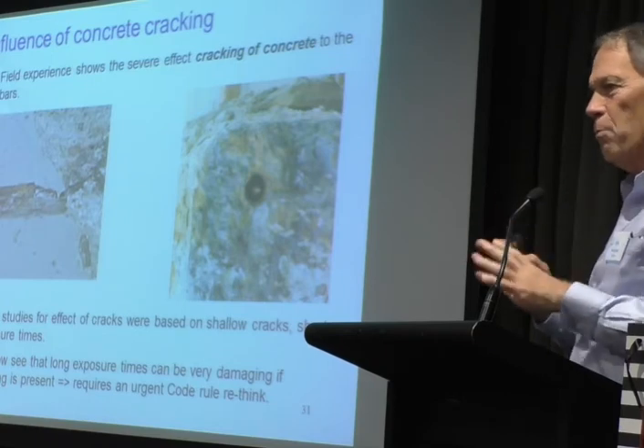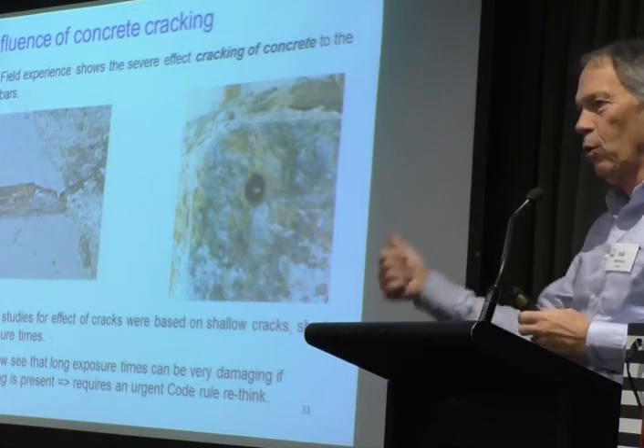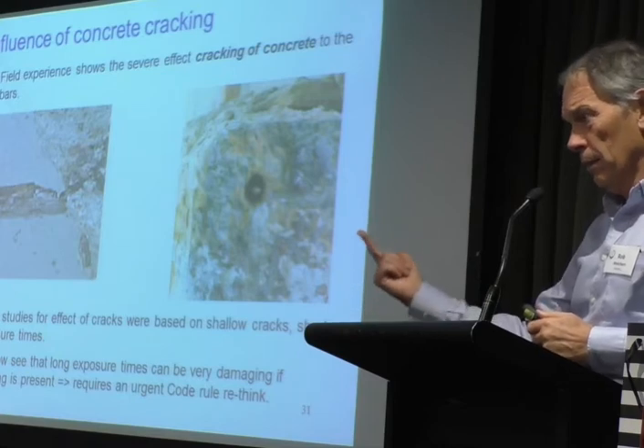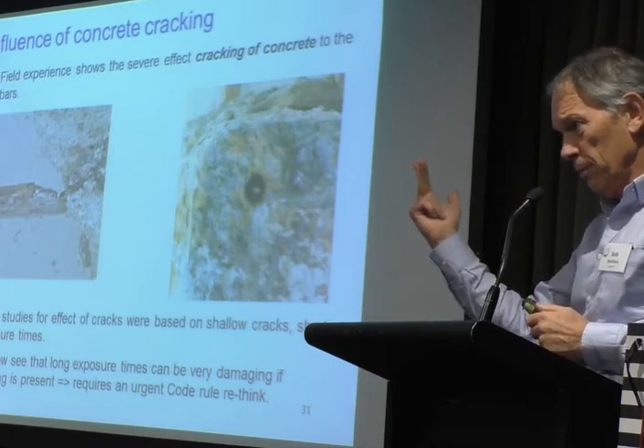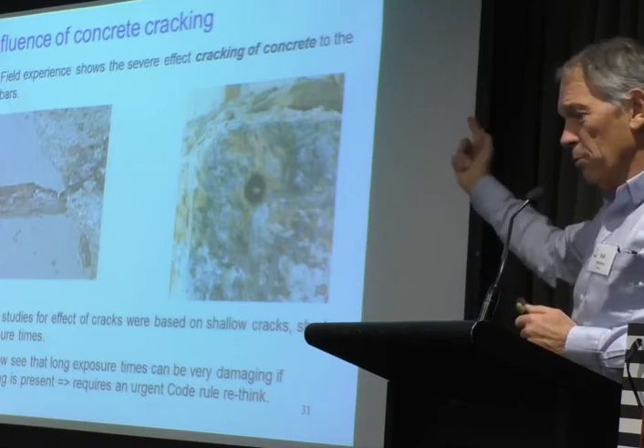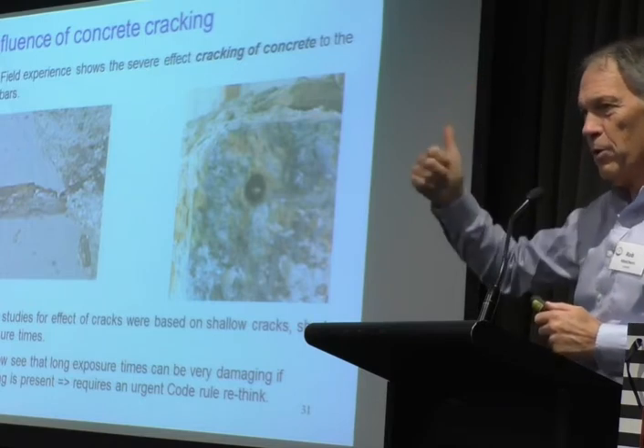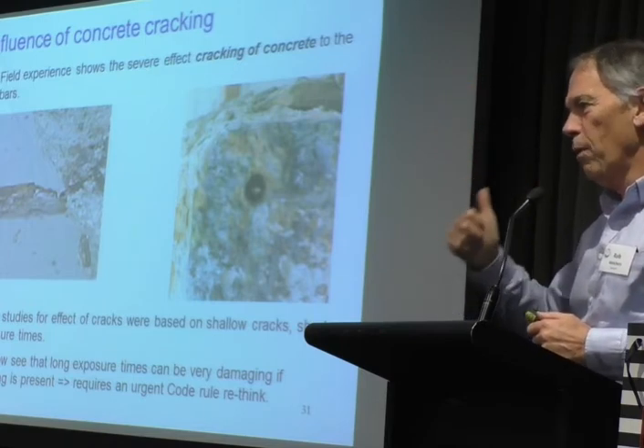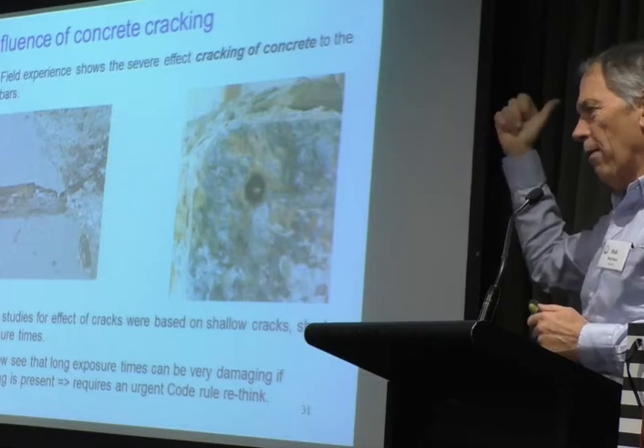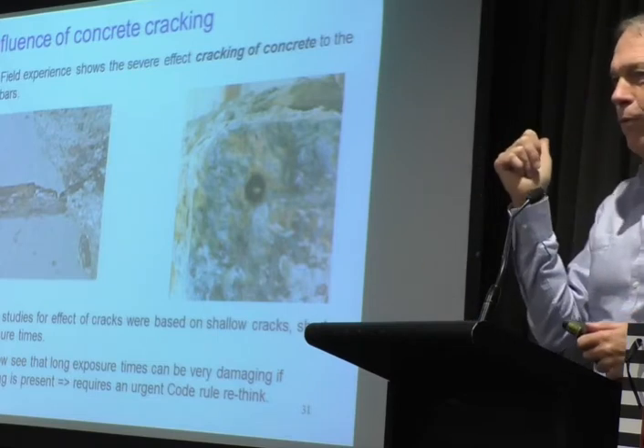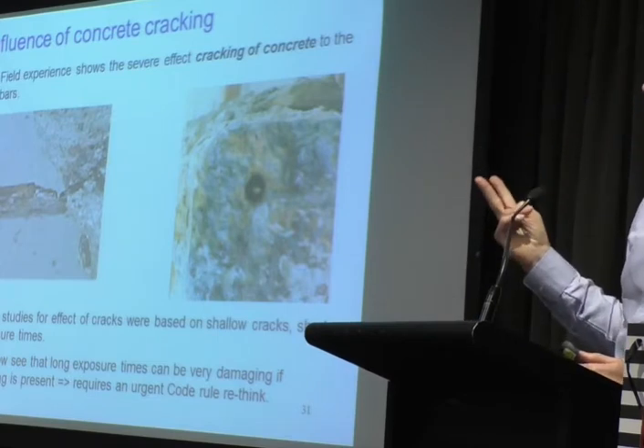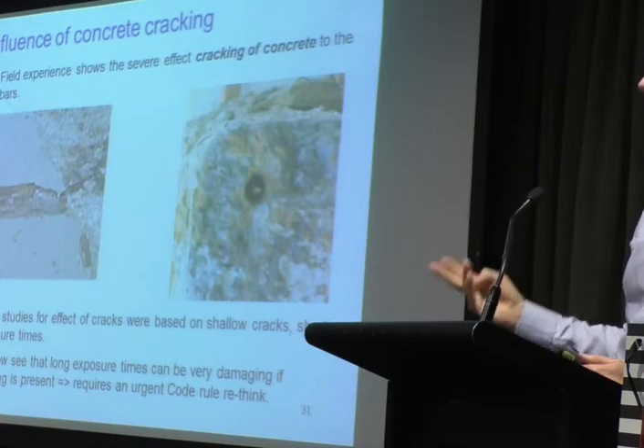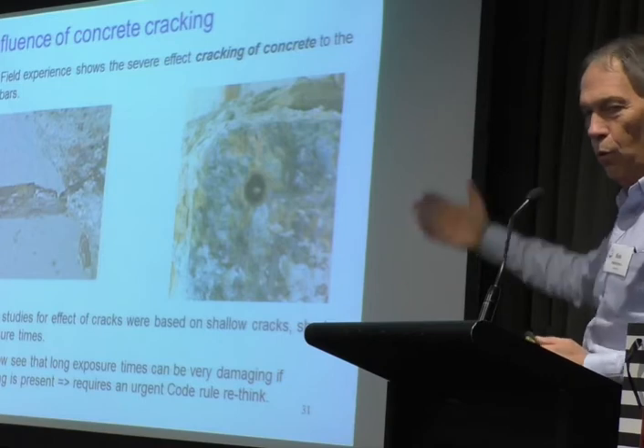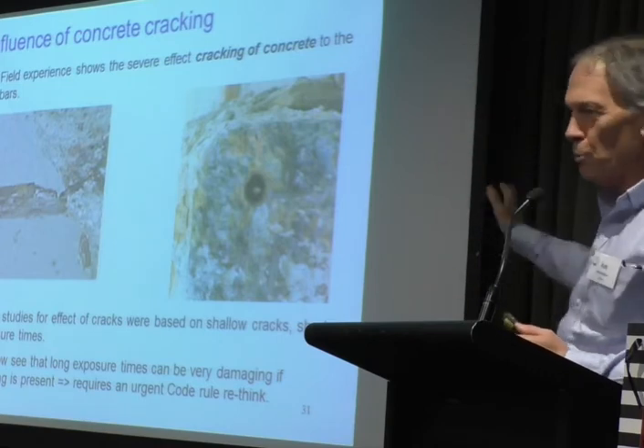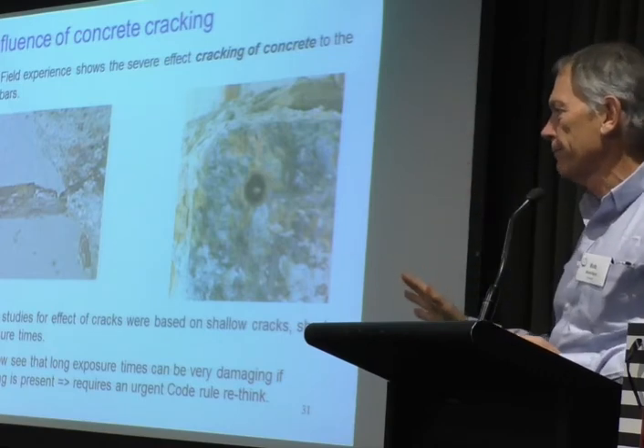And if you go back and look at the fundamentals, we've got chlorides, iron, a little bit of oxygen. There's not much oxygen you can get in here, presumably. And ferrous chloride can form under these conditions. And ferrous chloride is one of only two corrosion products. The other one is ferric chloride, which is soluble. So they can flow out in watery conditions. All the other rust products can't do that. They settle out.